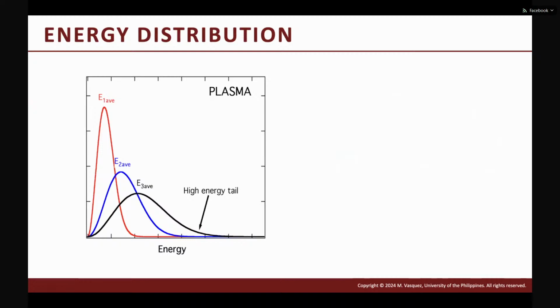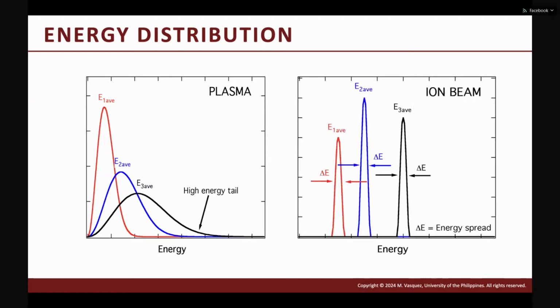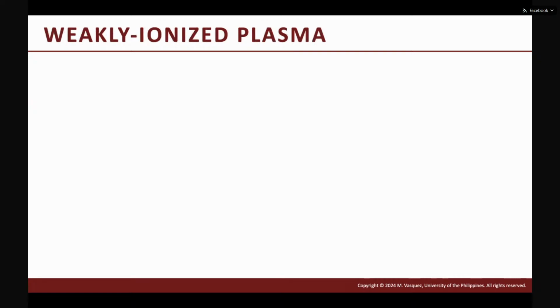In terms of energy distribution, plasma follows this Maxwellian type distribution, and you always have this high energy tail of the plasma. The population may be small, but sometimes the effect of these high energy ions or atoms can be detrimental to your process, like if you're developing a device. So sometimes you can narrow down the energy distribution by extracting the ions, and you produce an ion beam. So with ion beams, you have a narrower energy distribution, which allows you to have more control of your process.